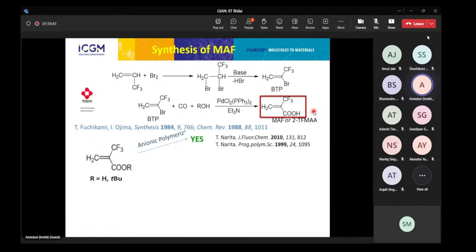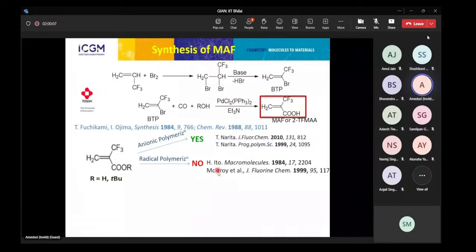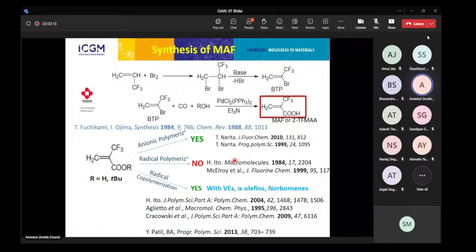And indeed, when you look at the literature, Professor Narita in Omiya in Japan made a lot of anionic polymerization. And it works because you have two electron-withdrawing groups. CF3 is electron-withdrawing, the ester is electron-withdrawing, so this can be done by anionic polymerization. However, in radical polymerization, you make oligomers with very low DPn. So Ito and McElroy did some work, but they didn't show that they could make radical polymers with high molecular weight. But because it's electron-withdrawing, it can react with electron-donating comonomers, just like vinyl ethers, alpha olefins, or norbornene. And Hiroshi Ito at IBM, Aglietto in Italy, and even we did some work of copolymerization with vinyl ethers, and it was successful to show that they were alternating copolymers.